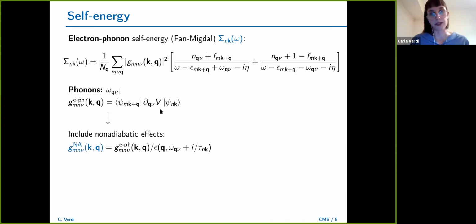There is an additional caveat, which is the fact that it is important to include in these calculations non-adiabatic effects. What does this mean? When we dope the material, there are these additional electrons in the conduction band bottom, and these electrons can further screen the electron-phonon interactions. And this needs to be taken into account in a dynamical way by further screening the electron-phonon matrix elements by the electron dielectric function, which in this case can actually be approximated by the dielectric function of an electron gas, because we're just describing the electron gas at the bottom of the conduction band.